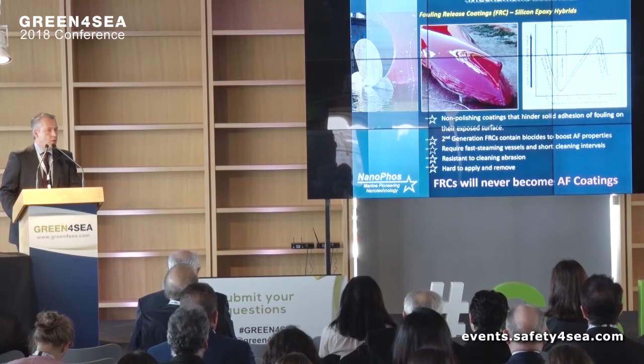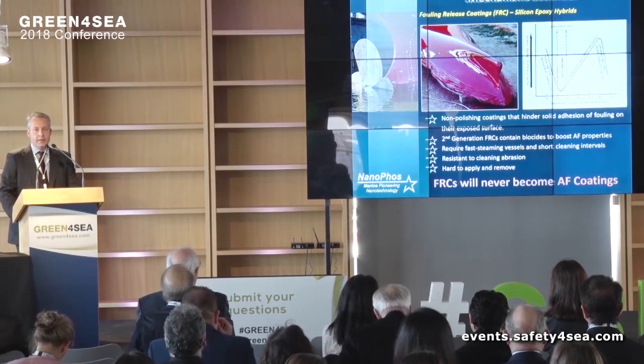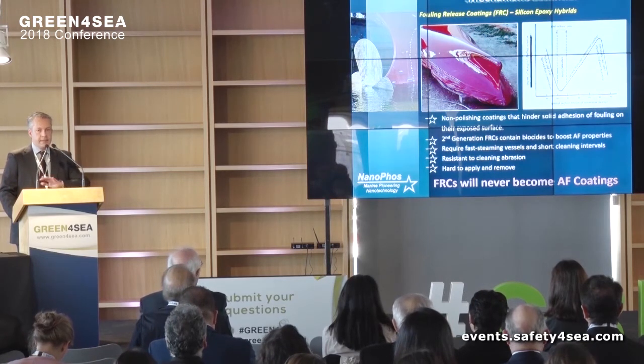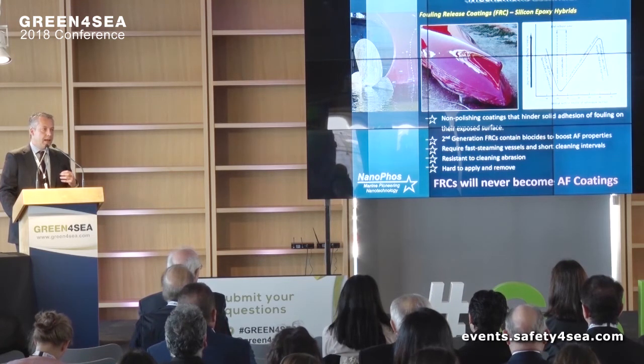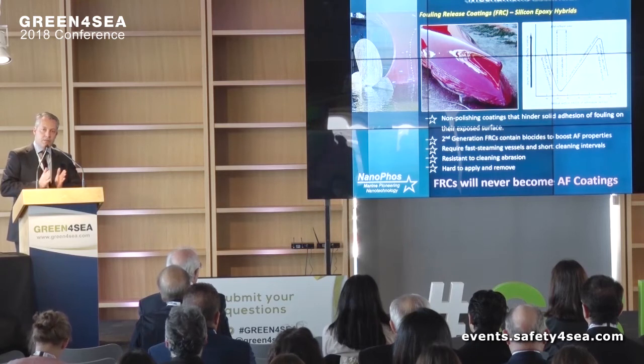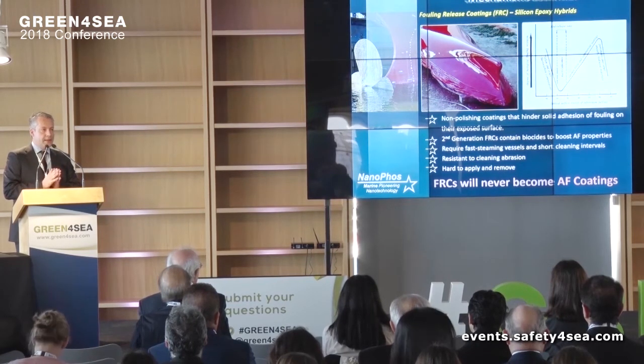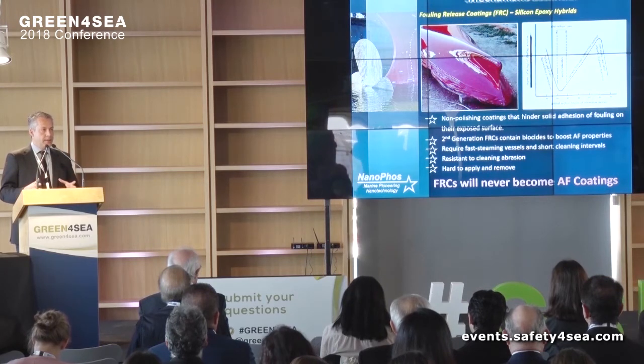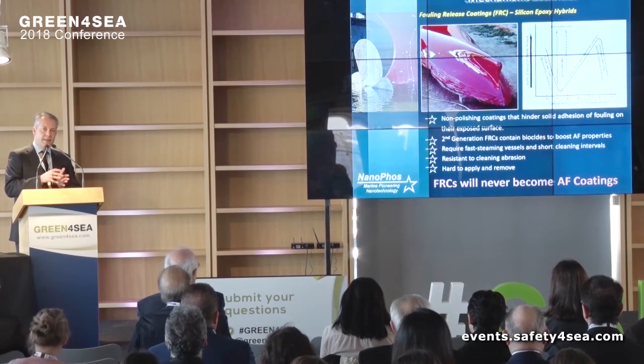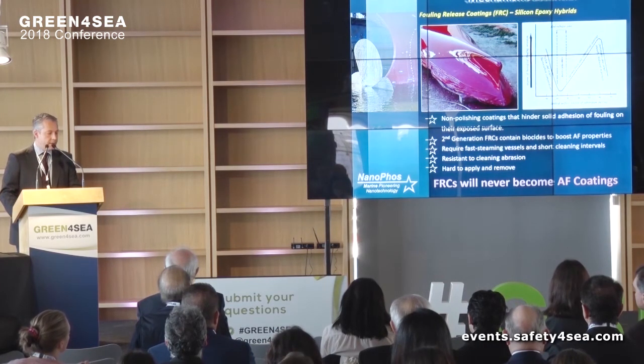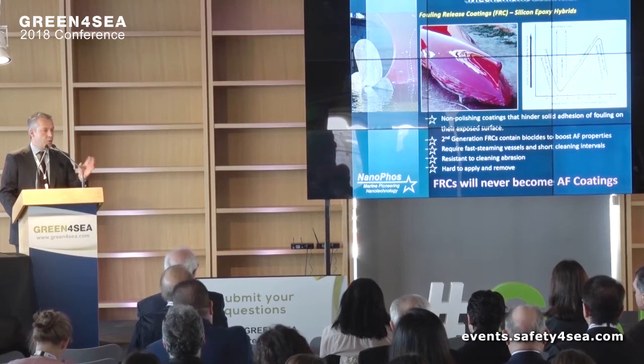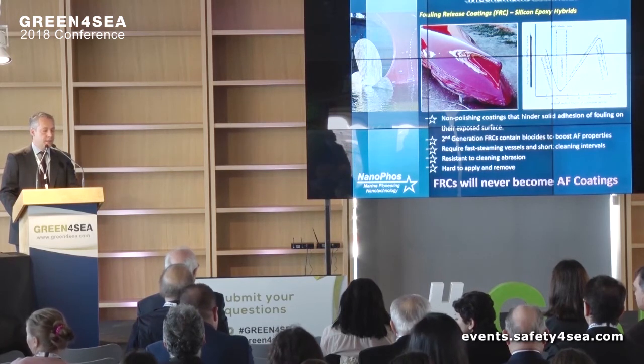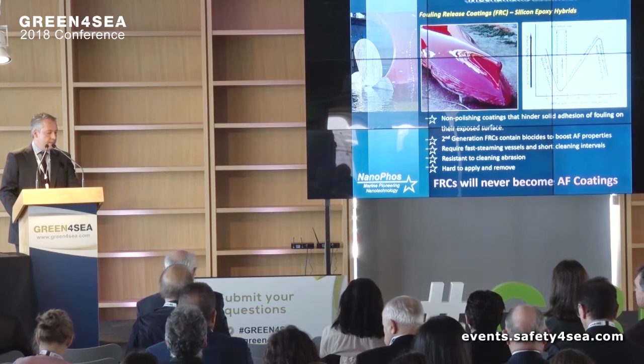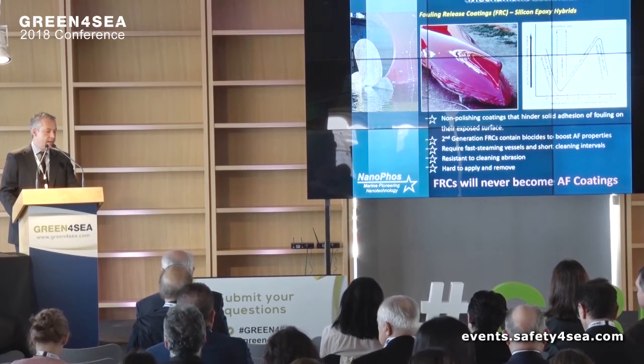Another technology that developed in the last decade is the fouling release coatings. Those are coatings that are very, very slick, and they do not allow for a very strong adhesion of the biological growth to the surface. The adhesion exists, so in my opinion, fouling release coatings will never become anti-fouling coatings, but due to the friction and the movement of the vessel, and the fact that the adhesion is poor, the fouling eliminates and goes away. There are some surface properties that can help fine-tune these fouling release mechanisms. They are more resistant to cleaning, but they are very hard to apply and to remove.